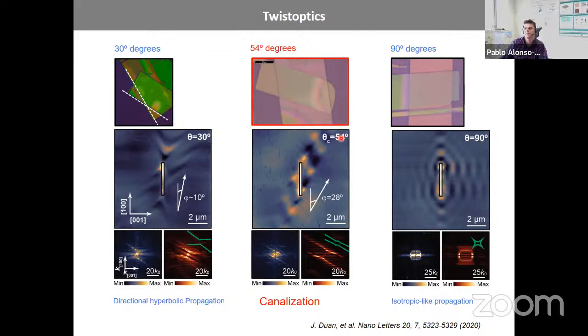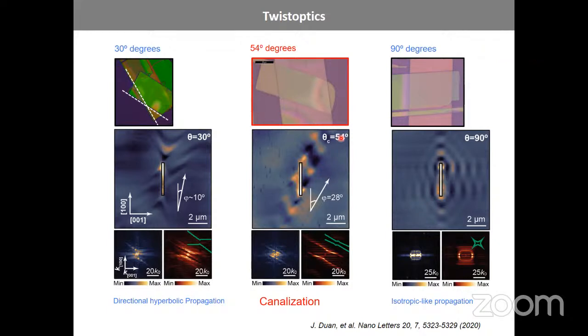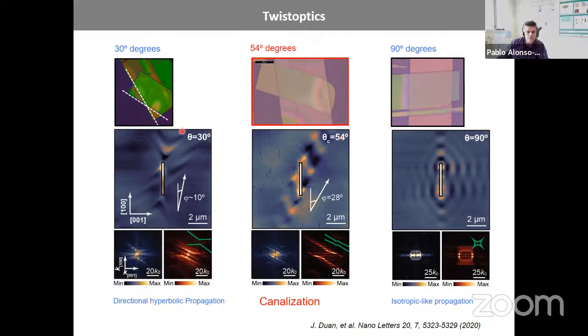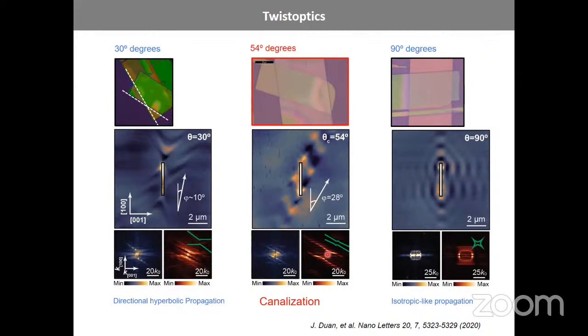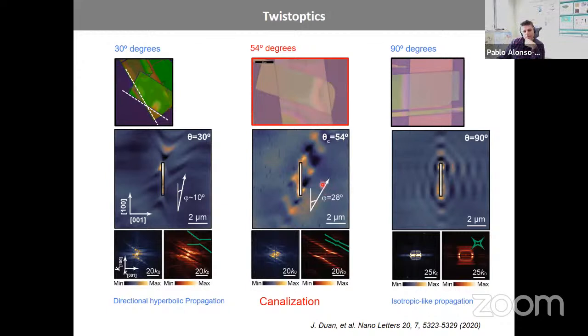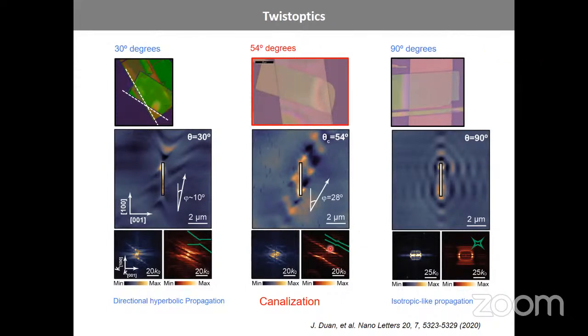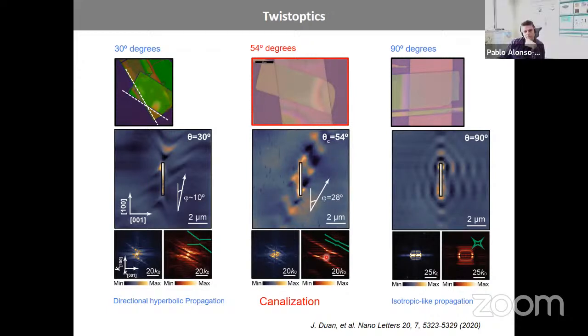Exactly. Okay. And then what is the role of the distance between the two flat bands, the two iso-frequencies? Does that affect? You mean this distance? Exactly. Yeah, this distance here is given by the thickness of the flakes. In principle, if one tunes the thickness of these two flakes, one can make them larger or smaller. For the collinear case, which is somehow dominating sometimes, I mean that the K vector goes here and the Poynting vector is collinear, because this is dominating somehow in the images.